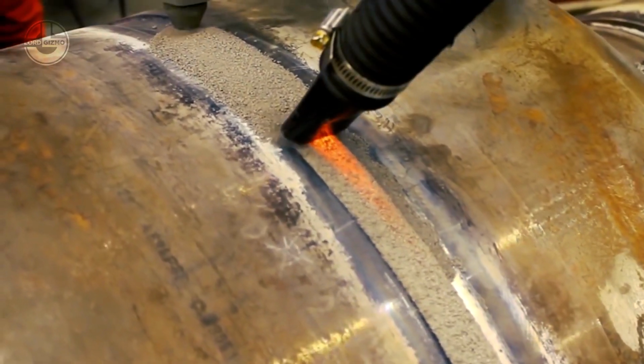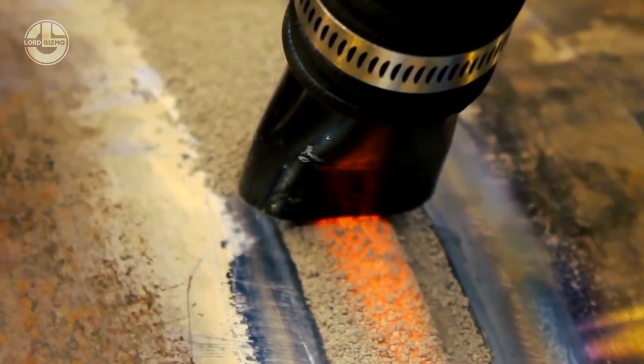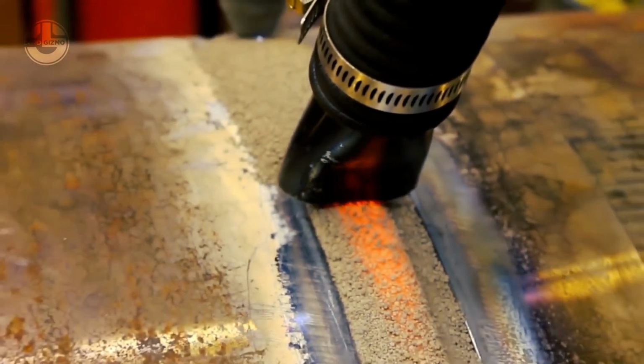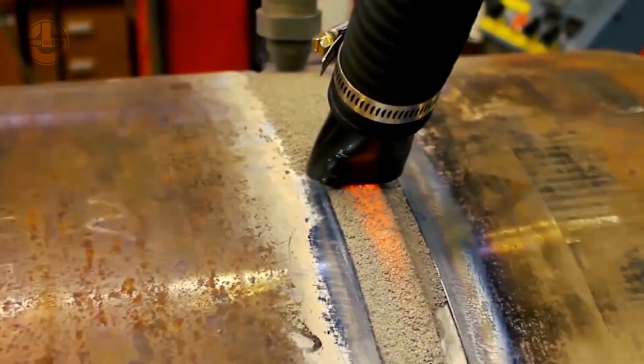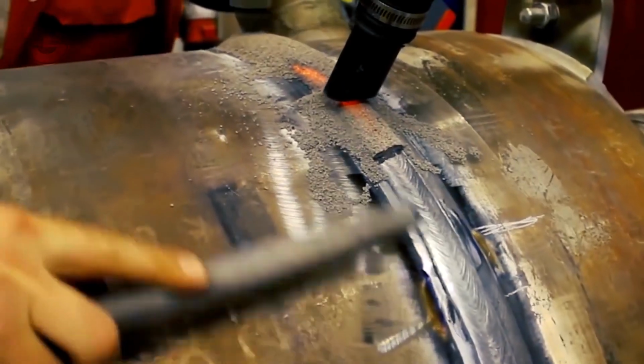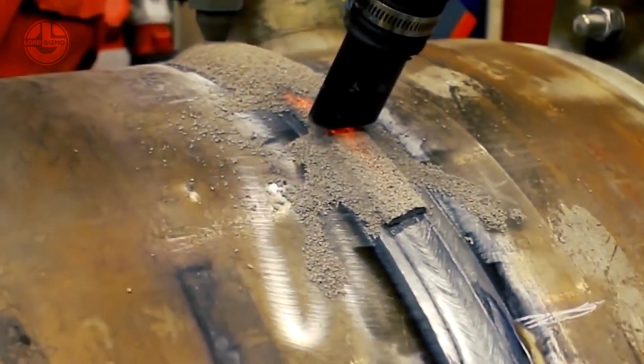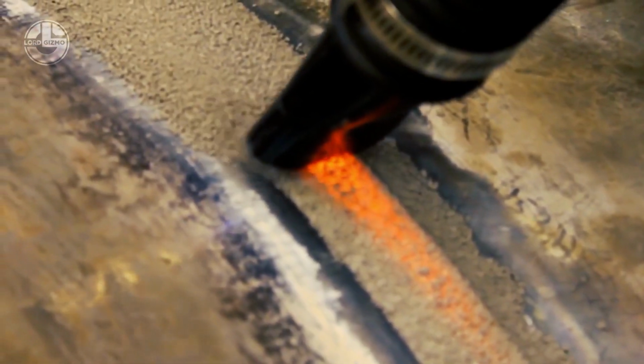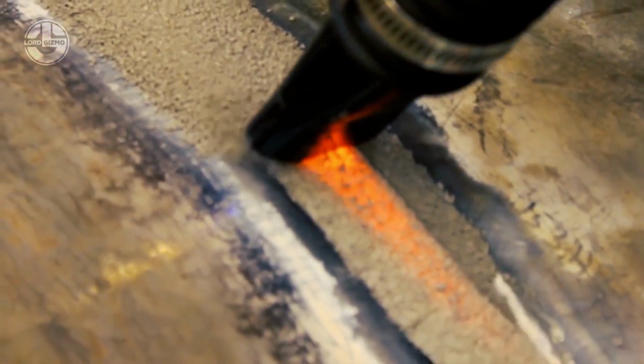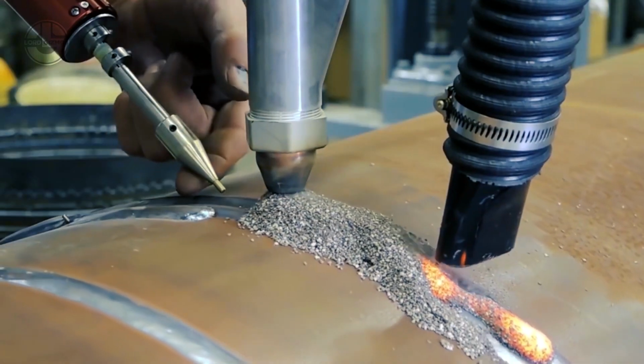Here are some of them. Number 1. Operation. In SAW, a blanket of granular flux is placed over the welding arc, or the arc is submerged beneath it. The flux has several functions, including shielding the arc, producing a gas for shielding, and forming slag to cover the weld pool as it solidifies.